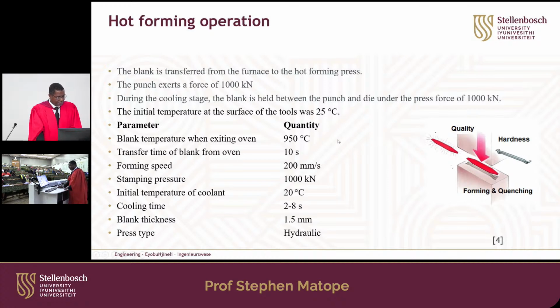And those were the properties of our blank. Our blank was at 950 degrees Celsius. The transfer time from the furnace to the forming press was 10 seconds. Then the forming speed, how we moved it down, our punch moved down to come up with the final product at 200 millimeters per second. Right, all goes down like that.